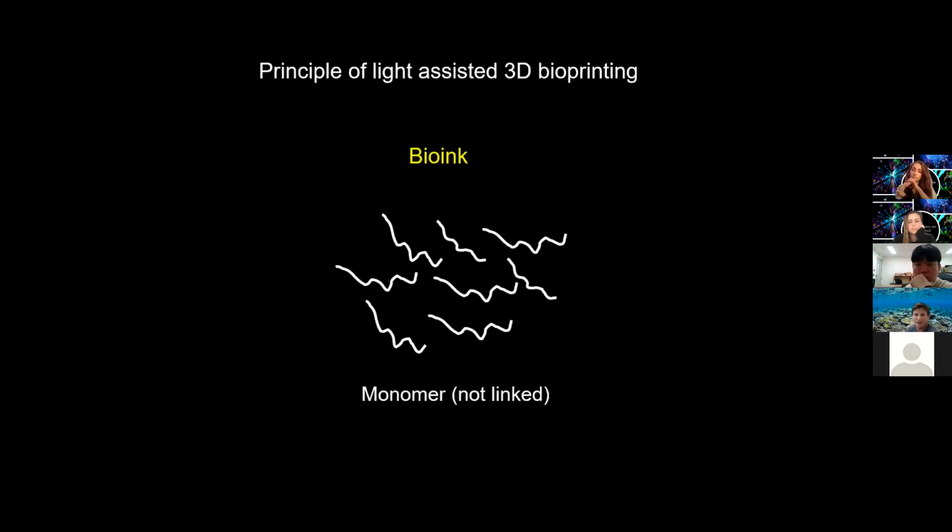And then for the bioprinting approach, we used light-assisted 3D bioprinting. So this relies on photopolymerization. So a brief overview on the development of the bioink. You have a monomer. In our case, we used gelatin methacrylate, and you add your cells, which are different strains of microalgae cells.